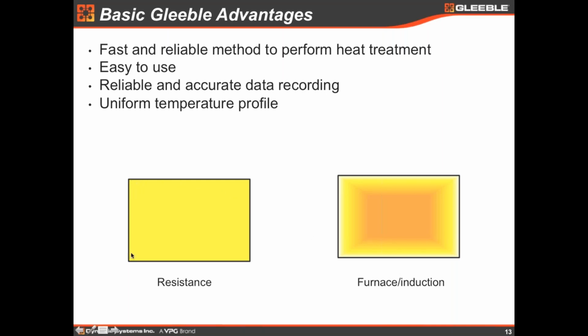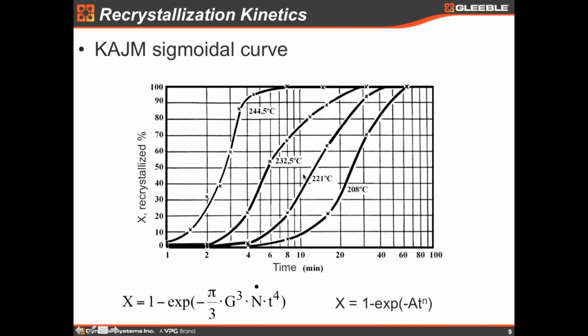And the reason is, let's say this is a cross-sectional area of a specimen, and this is the resistance heating, and this would be, let's say, furnace and induction heating. In furnace and induction heating, we start heating the surface, and then after soaking, it reaches the center of the specimen. On a lot of occasions, you have the specimen with this gradient for a long time. So we see here that it's hotter at the surface than in the center. Let's think that we have, let's say, 20 degrees difference in temperature from the surface to the center of the specimen. So let's come back here to this figure. You see the effect of just 12 degrees on the recrystallization kinetics.